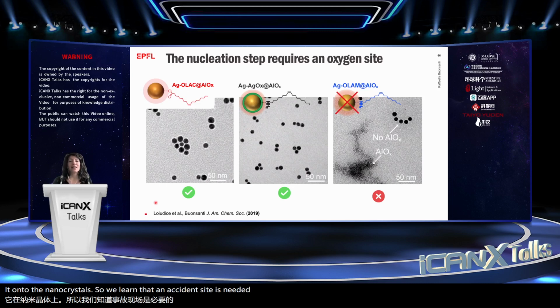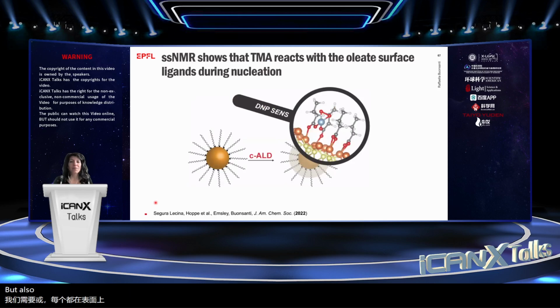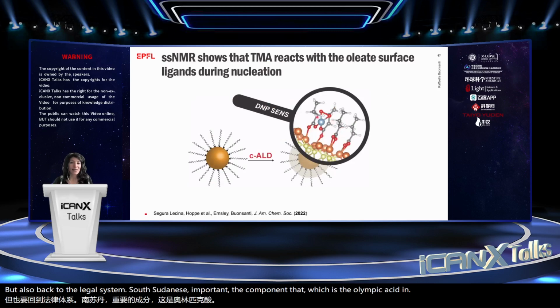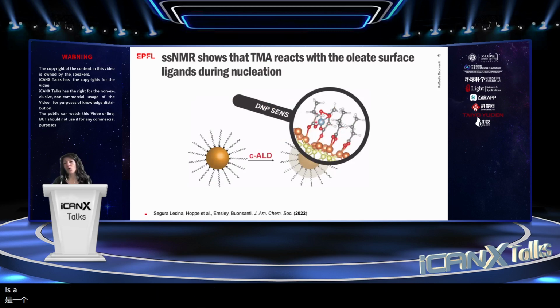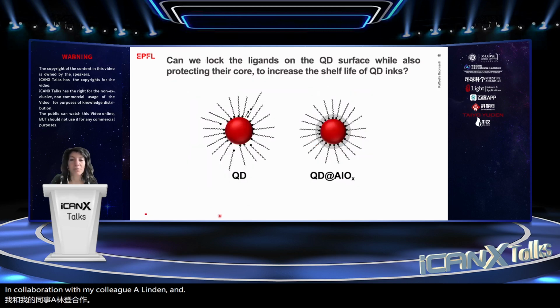And that we need OH basically on the surface, but also that the ligands themselves, so this important component, which is oleic acid in this case, can also act as nucleation site for the trimethyl aluminum. And this was revealed by running some solid-state NMR in collaboration with my colleague Lyndon Emsley.